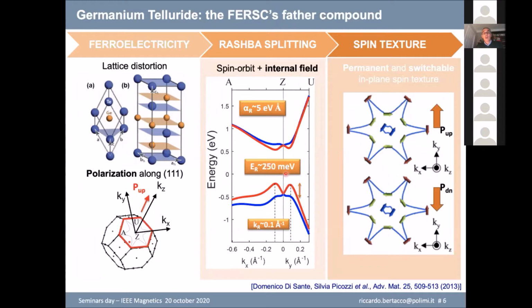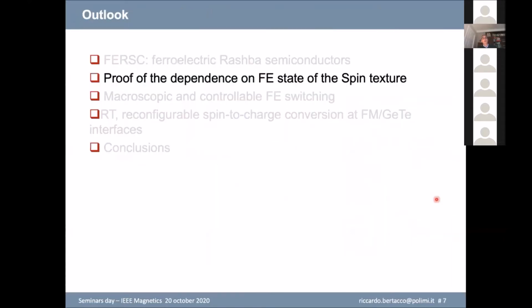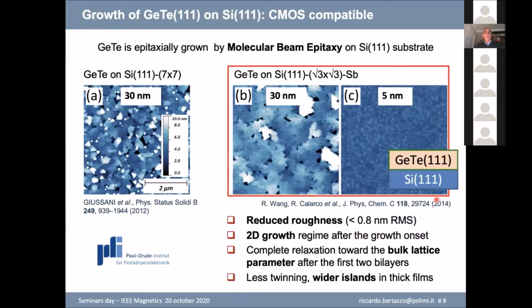And the beauty of the story is that the energy separation of these bands here is high, 250 millielectronvolts or something around 250. Now, the shape of the iso-energy cuts is not simple like in the case of the electron parabola, but you see you have some stars here, and the result of a calculation by Silvia was, okay, for up polarization, sorry, you have a sense of circulation of the spin which is different from that you can have for the down polarization. This was, I'll say, the beginning of the story, and now let's try to see what happens in practice.